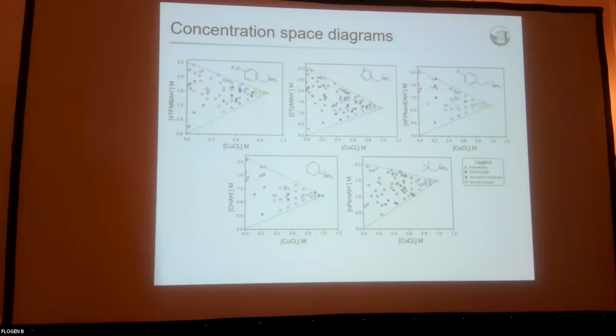But there are certainly some commonalities. We see a few big classes of material. We see some perovskitoids, 2-dimensional perovskitoids, copper chlorides. We see what I would call hybrid materials. In this case, I'm defining hybrid materials as compounds with direct copper nitrogen bonds. And then we see some situations like here in red where we're just reprecipitating some of our ammonium iodide salts as we allow the anti-solvent to be used.